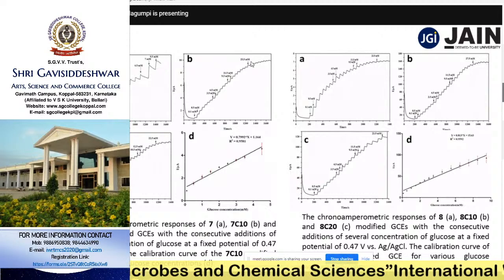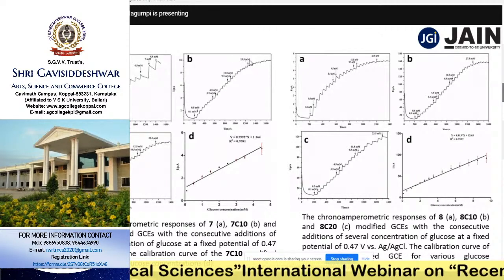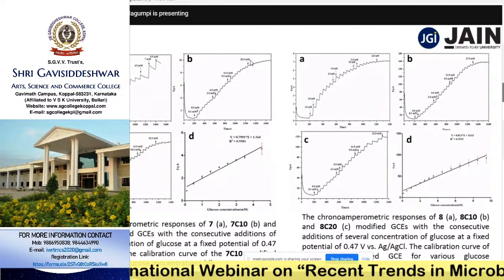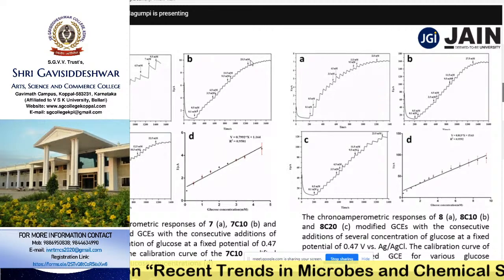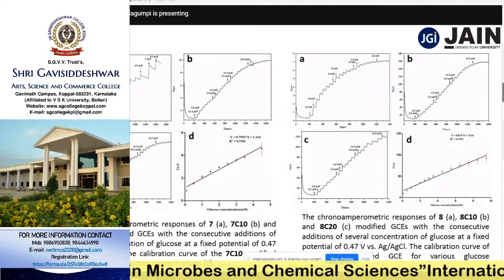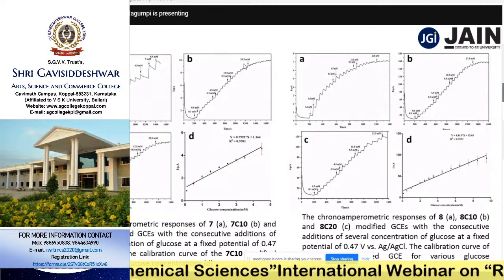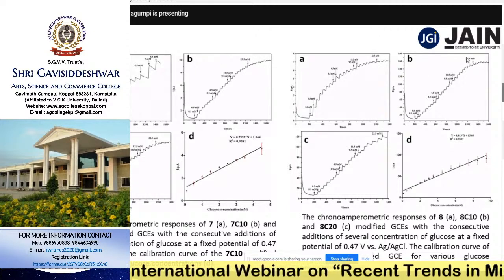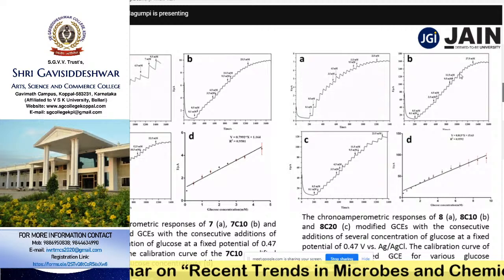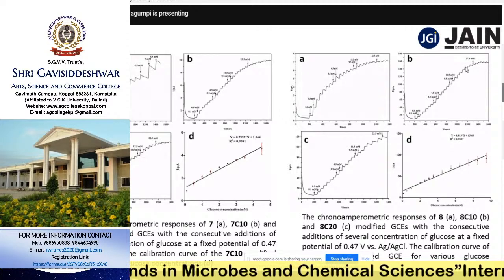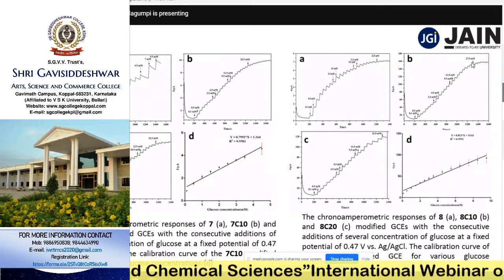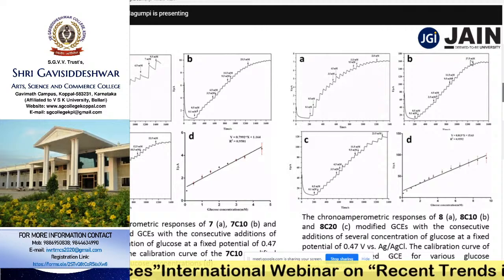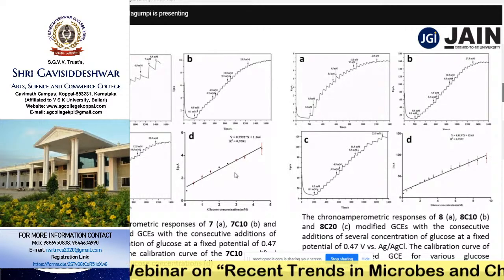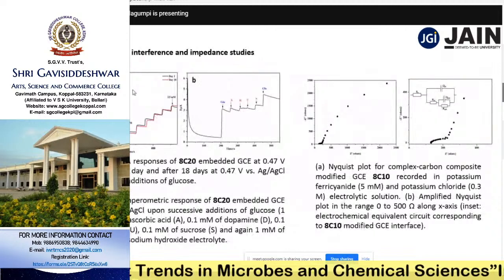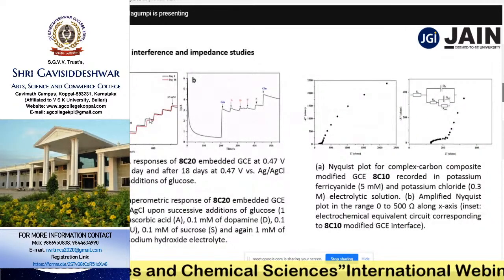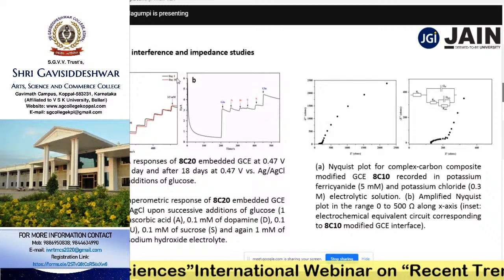Here one can easily identify the glucose up to 25.5 millimoles. So for a healthy person, the glucose concentration in the blood samples is around 4 to 6 millimoles, while one can easily identify the glucose concentration of up to 27.5 millimoles using these complexes. Hyperglycemic concentrations can also be measured accurately using these modified complexes. Further, we have done the stability studies here. This particular catalyst was stable up to 18 days.